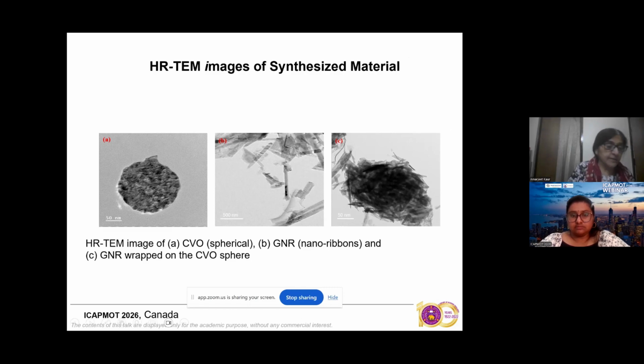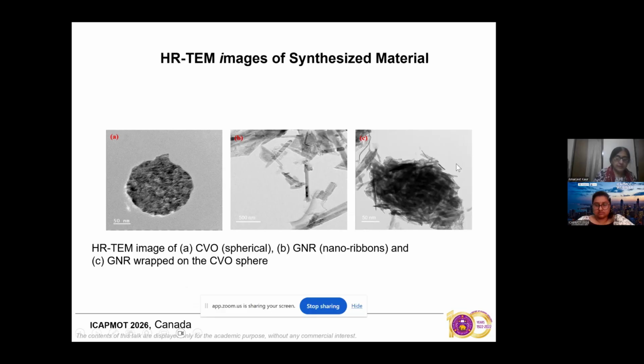The d spacing in the case of CVO is around 1.47 angstrom, and there are two kinds of planes present. Co3V2O8 is also present here, and then we have this CVO GNR. In this one can easily see that within these ribbons, the CVO nanoparticles are entrapped.